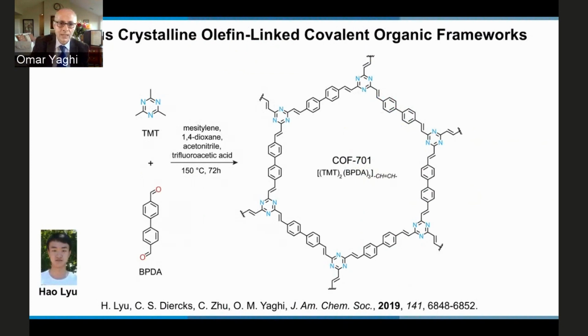Of course, the ultimate in making robust materials is to make carbon-carbon bonded materials. And so here you see how we are able to make olefinic materials that are linked by carbon-carbon double bonds. Here the original conditions are there, but we added acetonitrile and trifluoroacetic acid at a slightly higher temperature. But you make this beautiful structure, where the temperature is not so high as to not allow the organics to survive, but low enough that you can preserve the character of the organic, which is something you need later in terms of functionalizing the structure.